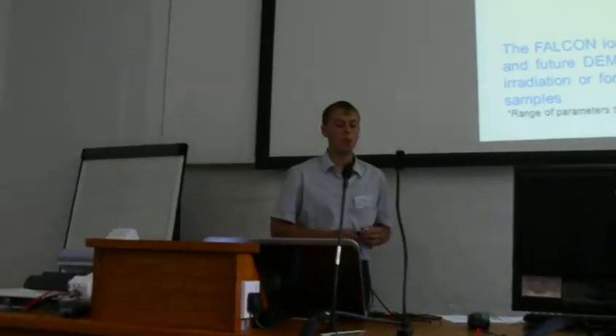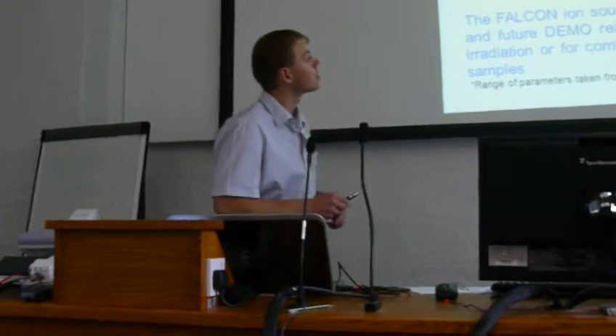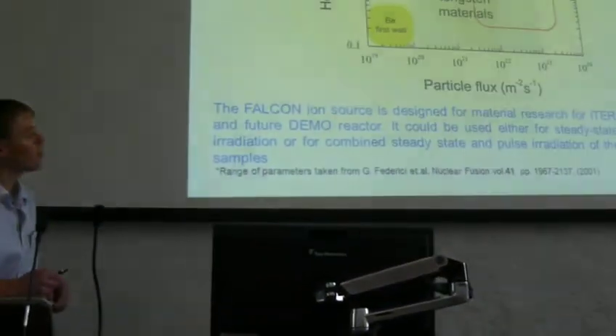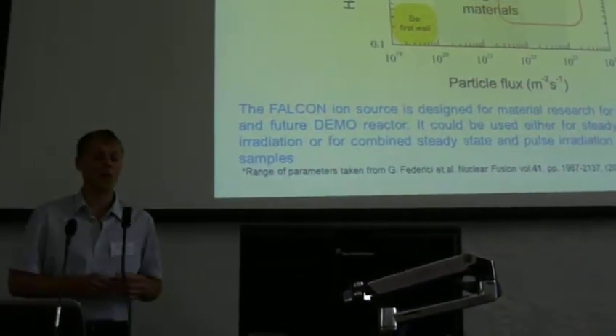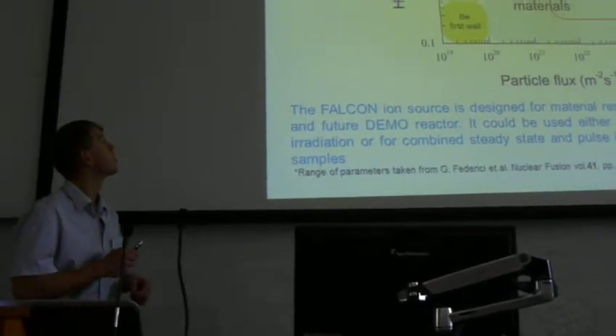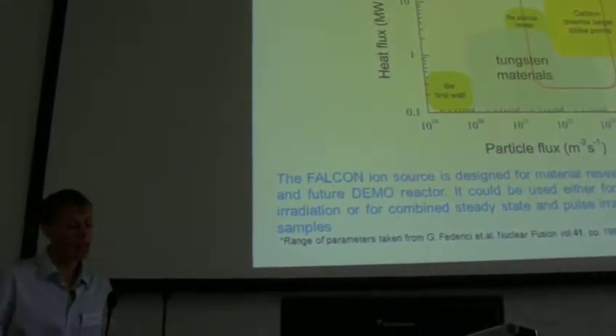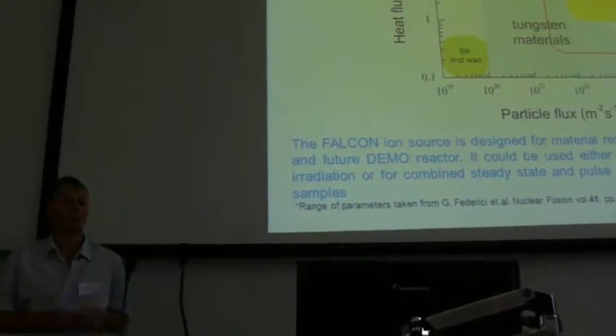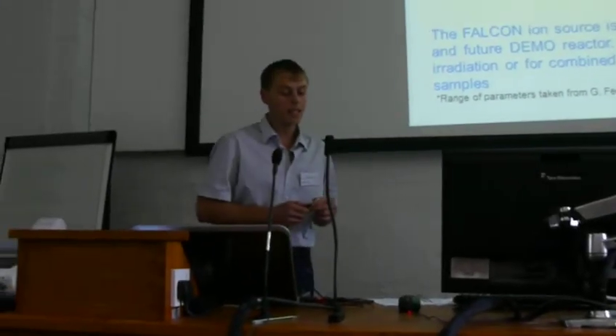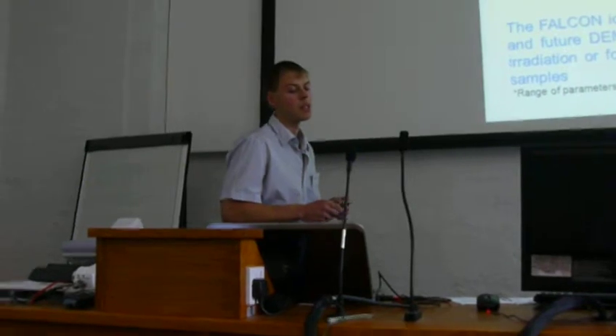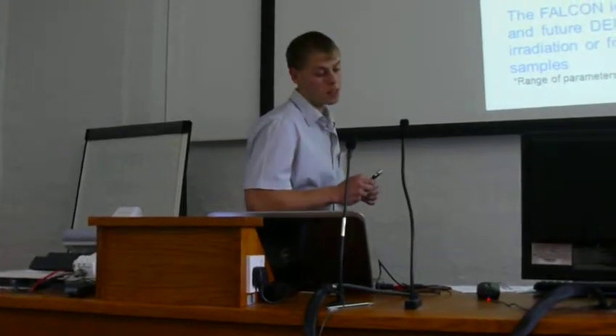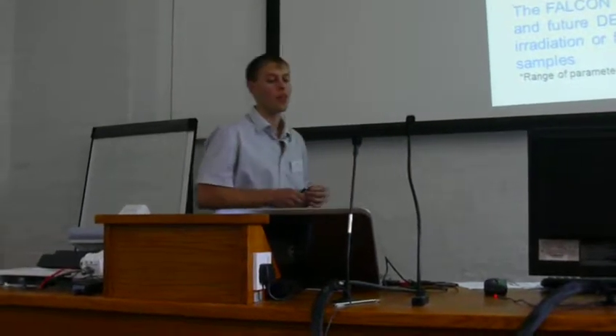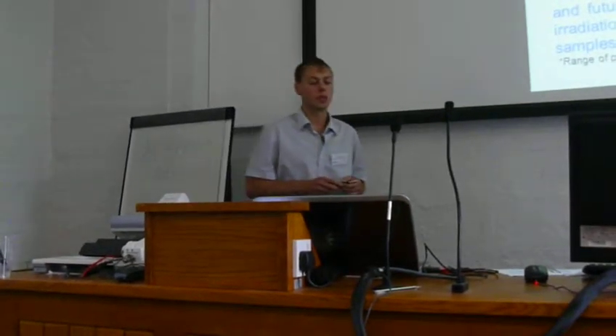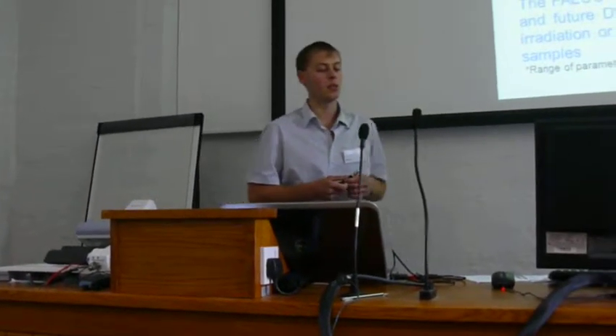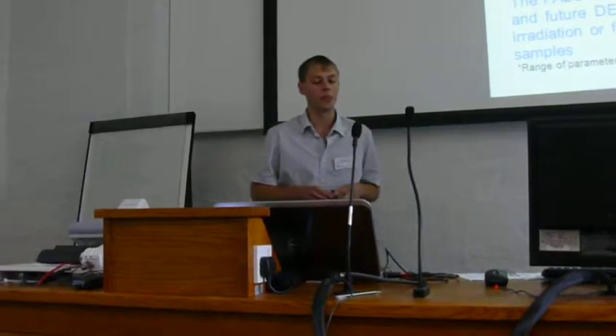Conclusions. Falcon source produces a particle flux above 10 to the 20 power per square meter per second and up to 20 megawatt per square meter. This covers the radiation parameters range for plasma facing material almost entirely. Therefore, the Falcon ion source is suitable for material research for ITER and future DEMO reactor.